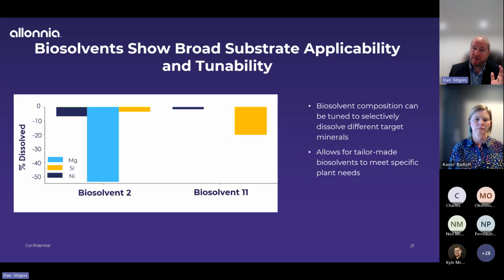Additionally, we see that from the same substrate, we can tune the composition of these solvents, as we mentioned earlier, by changing the way we raise the bugs. And by doing that, you can essentially generate a new type of extractant that could be more specific for a particular gangue mineralogy versus others. And here you see a piece of data that's similar to what Karrie showed with Biosolvent 2, where we're looking at trying to remove magnesium. And then another one that we've developed where we're now starting to look at silica and removing certain types of silicates that are present in these concentrates and getting them into solution.